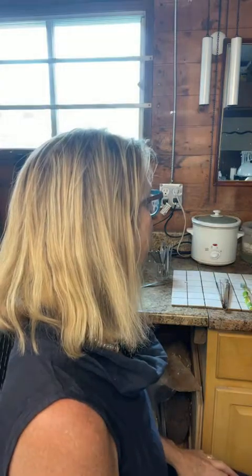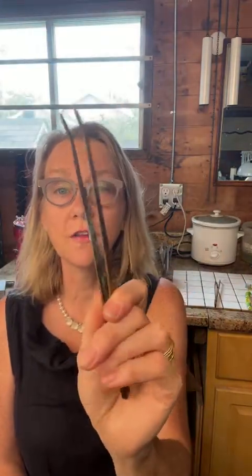And after things have been soldered, they go into, see if I can make that a little bigger. There you go. They go into what's called the pickle, and the pickle is like a very mild acid bath. They go in here. That'll remove the oxidization. I don't think I have an oxidized piece here. The application of heat with the torch will cause the piece to become blackened, even gold. And after it's cooled down, it will go in the pickle, where it removes that oxidization. And then in order to neutralize that acid, I have here baking soda water that neutralizes the acid. And right next to this is a sink. I will then rinse it off. And in the pickle, you can only use copper tongs. The steel tweezers would, anyways, it's a mess. You don't want to do that.